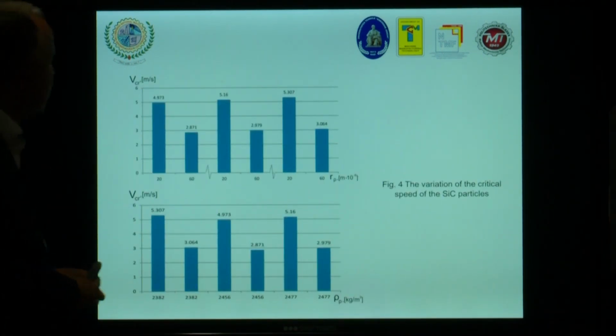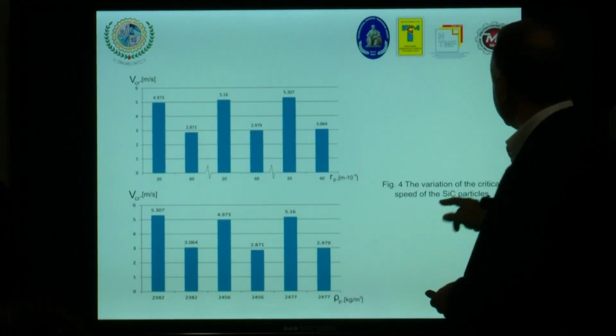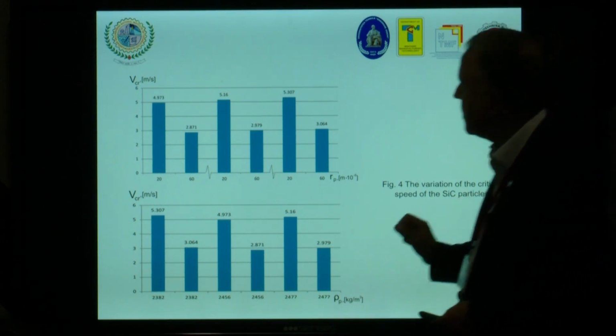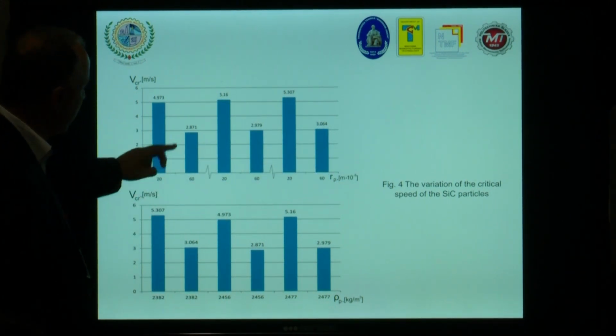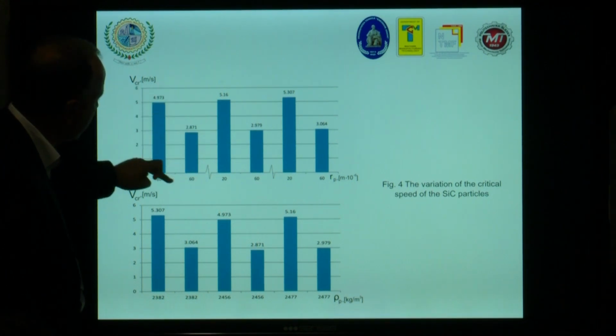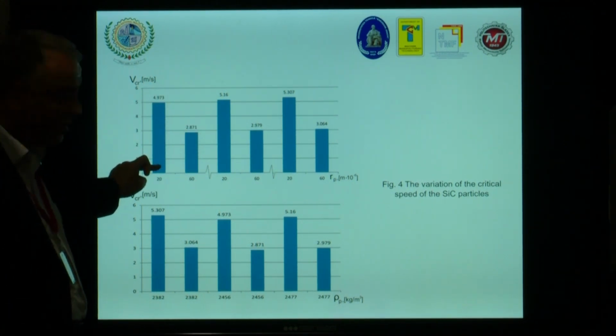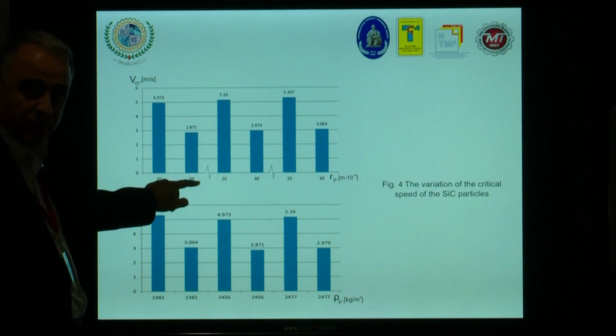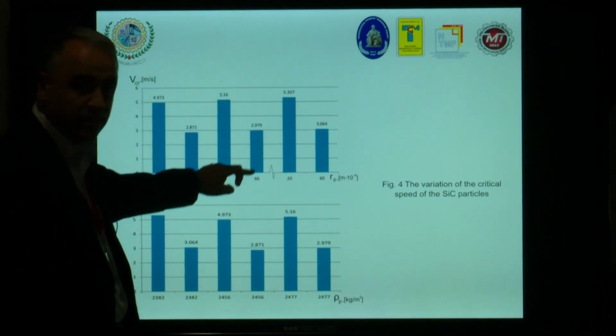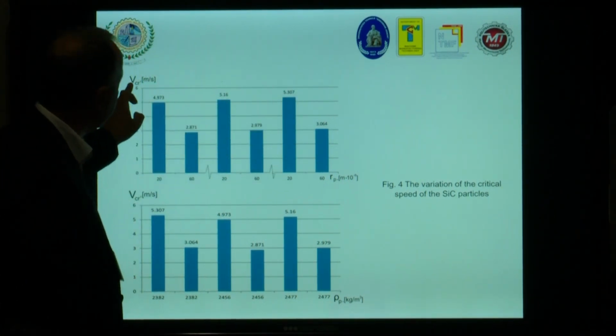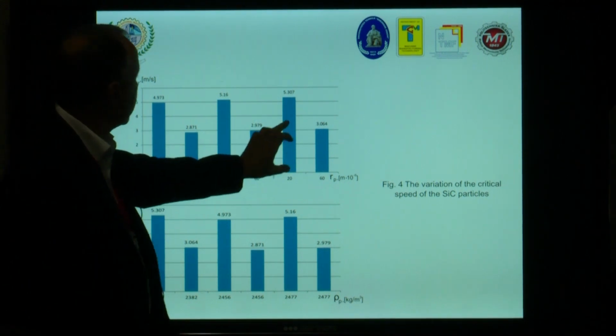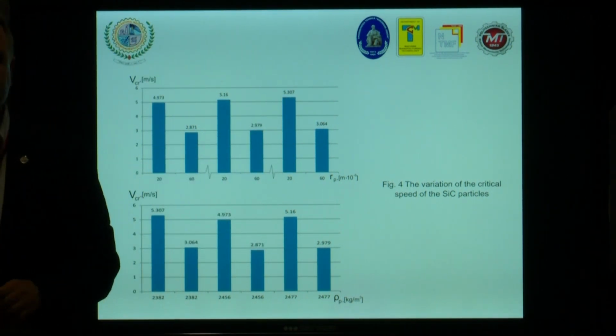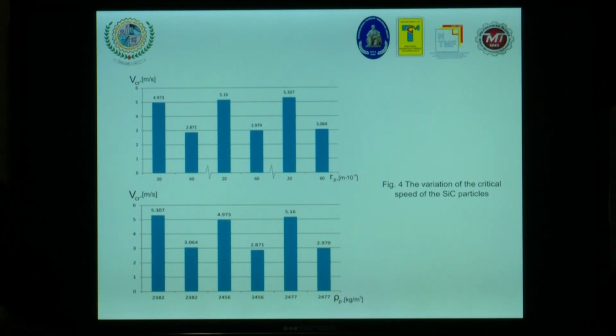And the first results are based on the variation of the critical speed of silicon carbide particles. You can see here two diagrams: critical speed and the radius, and which are the values. This is the result in case of the first alloy that we used with 2 values for the particle radius. This is the result in case of the second alloy, and this is the variation between critical speed and the radius in case of the third alloy. So you can see that the biggest critical speed, I mean the speed for transfer from gas to liquid, is in case of the third alloy that we used.